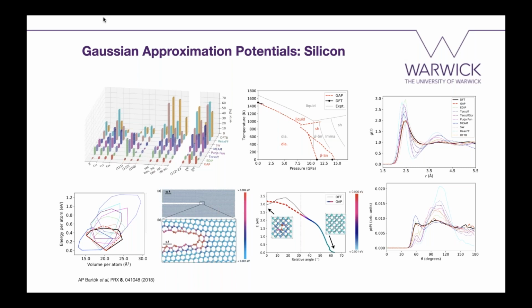What you can see here coded by the colors are the predicted errors that are coming from the Gaussian process error prediction. The method can actually quantify to a degree the error it makes on the prediction, and it shows in red those predictions where it's quite uncertain, and as it gets close to the bulk, the predictions are getting much smaller. So it's another nice feature that even though the method is not perfect, mostly because these configurations were not trained on, it makes prediction. It can also quantify the uncertainty.